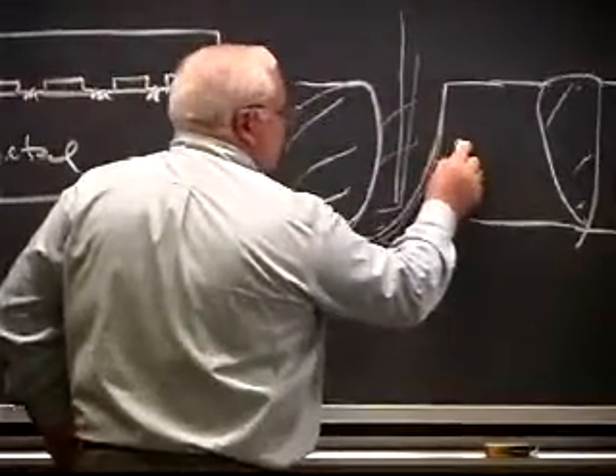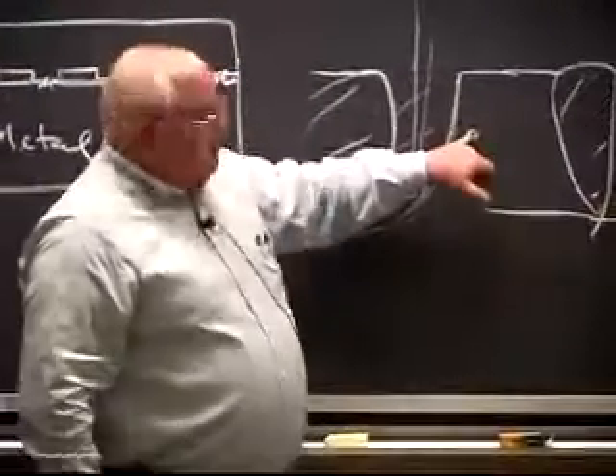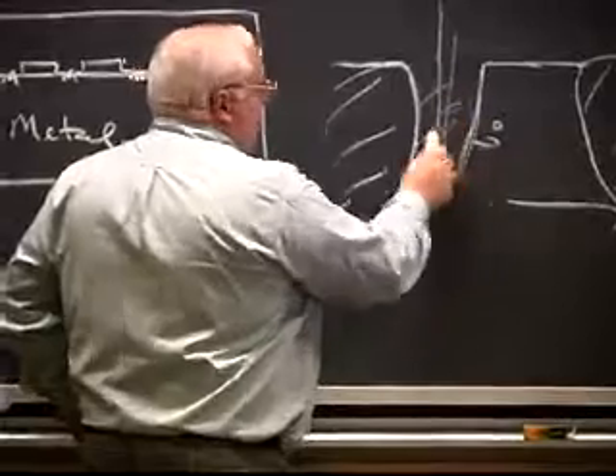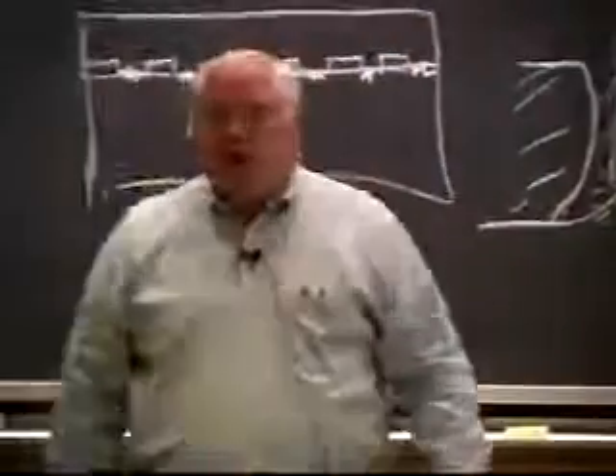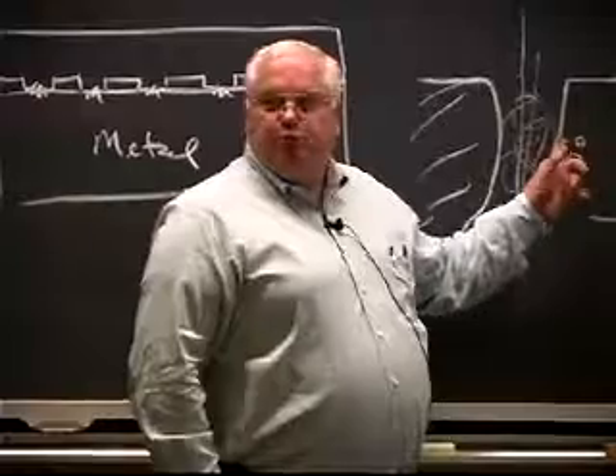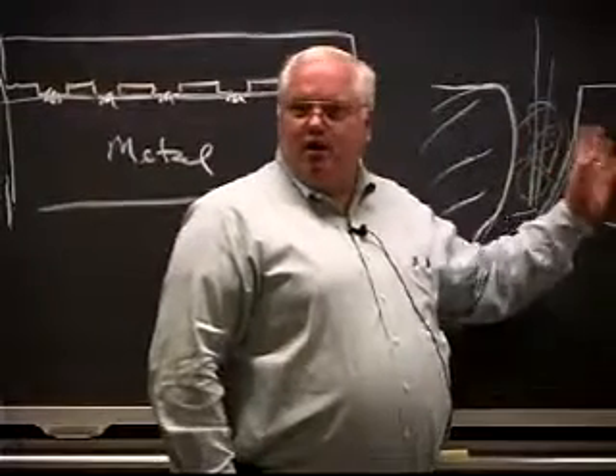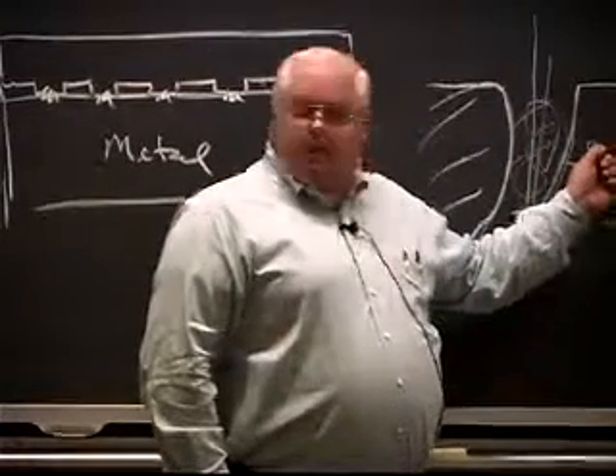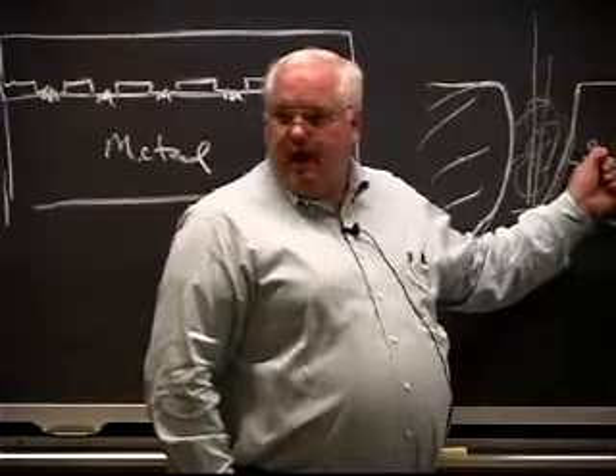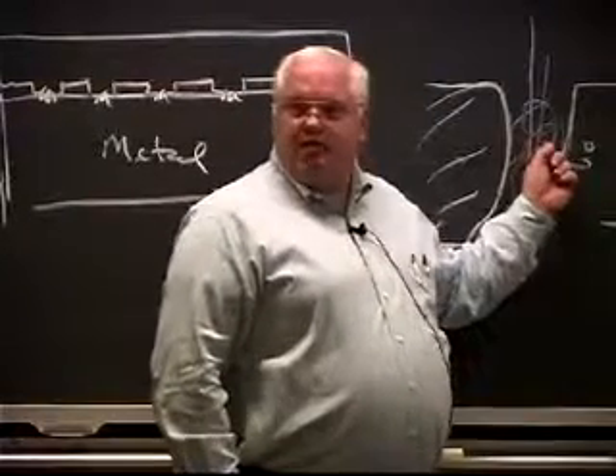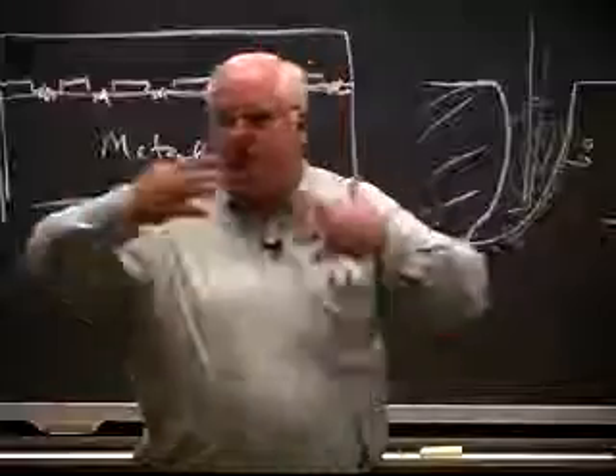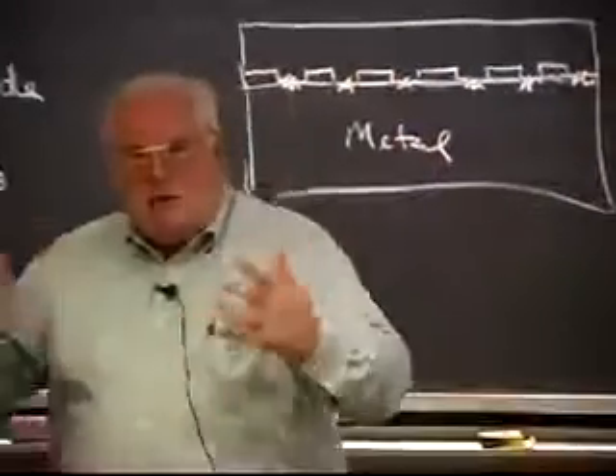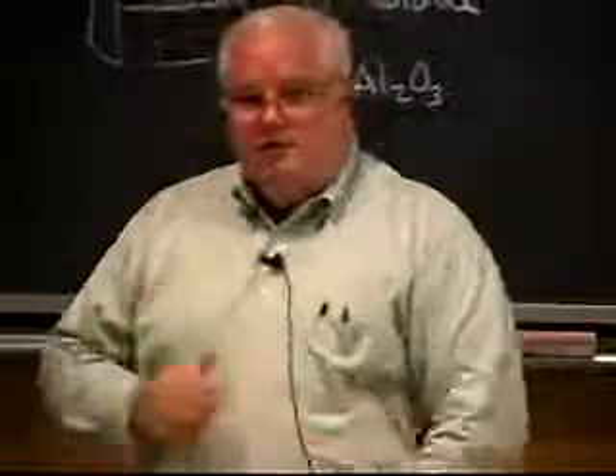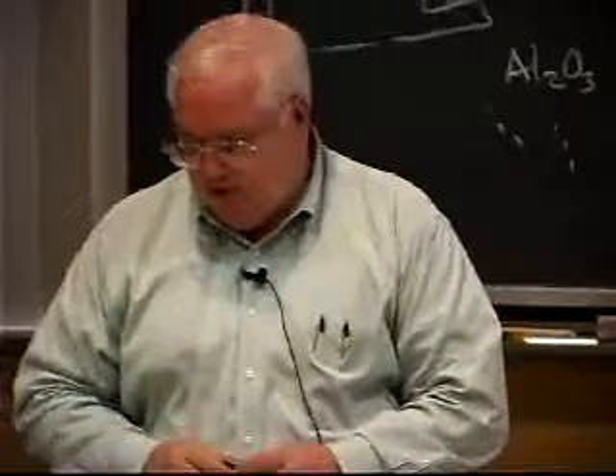of the defects. One thing they don't explain in the movie is every now and then you'll see a little black dot right in front of this thing, and it welds over the black dot. And when it welds over the black dot, you see black swirl inside the aluminum. That is a piece of copper. They drilled a hole and put a little copper wire in there, and they weld over the copper wire. Copper, being more X-ray dense than the aluminum, shows up black on the X-ray image. And when you melt the copper with the aluminum, it mixes with the aluminum, and you can see the swirling pattern as the copper mixes in on the aluminum. They don't tell you to look for that, but that's what they're doing.